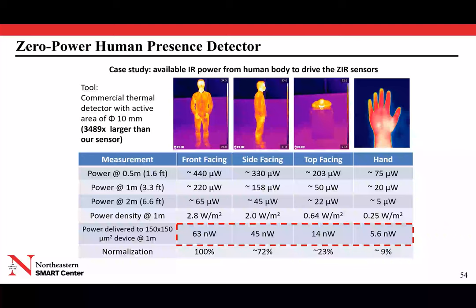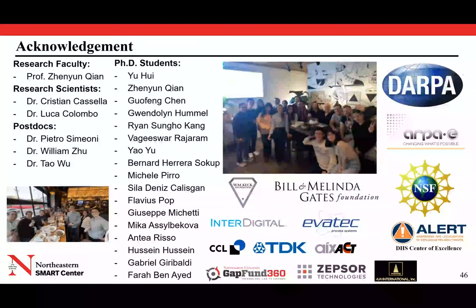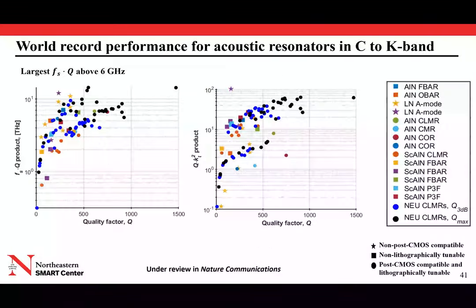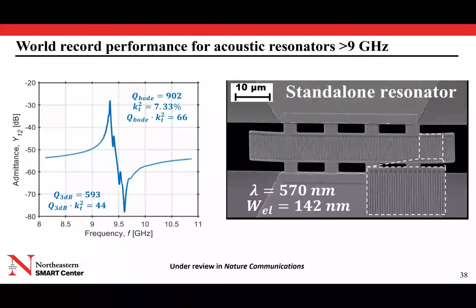That's a great question. One of the fundamental findings we had with this work on scandium nitride is that the whole community knew we could achieve high coupling doping aluminum nitride with scandium. That was well known, and there's quite a bit of work. But everybody felt that while we dope with scandium, the material becomes softer, and we thought it would be impossible to achieve the same level of quality factor achievable with aluminum nitride. What this work shows is that's not true. We are getting f times Q products very comparable with what you achieve with pure aluminum nitride, although we are doping with 30% scandium. I think that's really exciting.